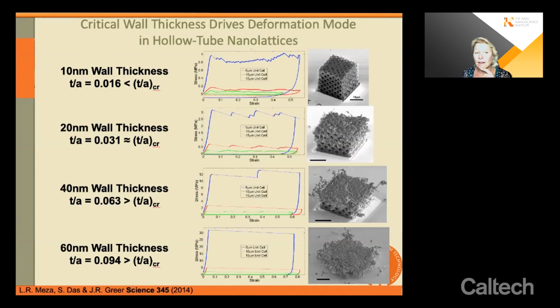When the T over A of 0.016 is below that, you can see from the data, first of all, full recoverability, and you can see the post-deformation image here, where you wouldn't be able to tell the difference before and after. Now, as you increase the wall thickness to 20 nanometers and further, such that the T over A ratio approaches this critical ratio and exceeds it, you can see that the deformation becomes much more stochastic and much more jerky. And this particular one, I believe, is similar to the video that I showed, and it doesn't fully recover. So that's the big difference: the presence of the buckling mechanism.